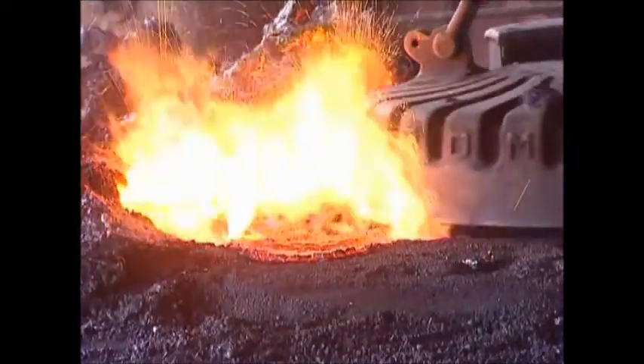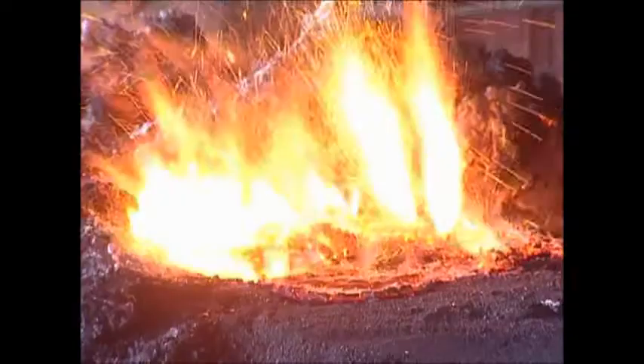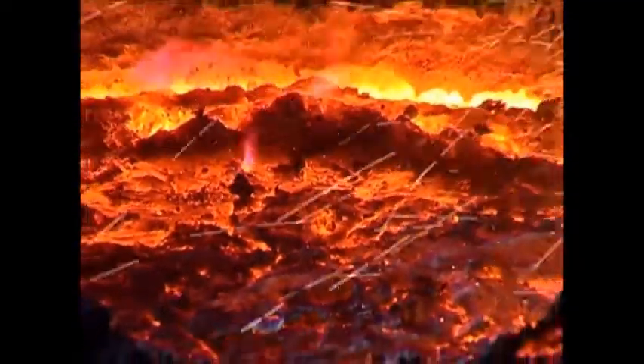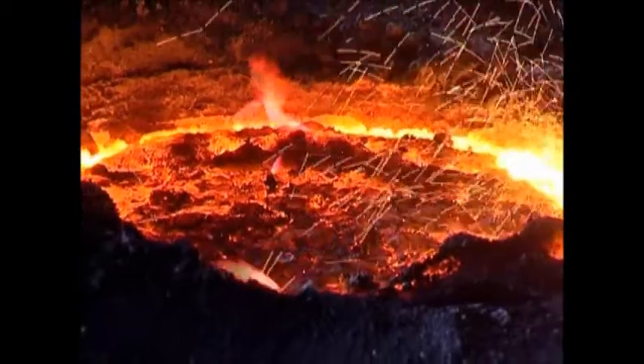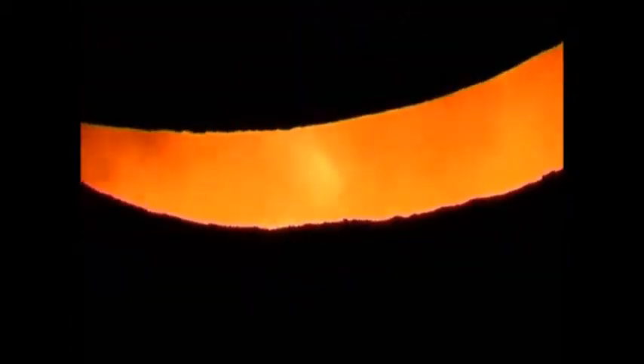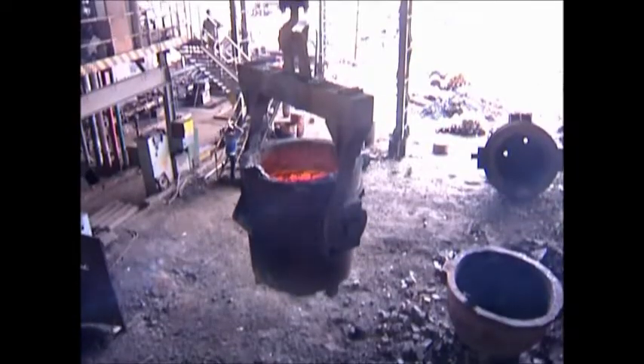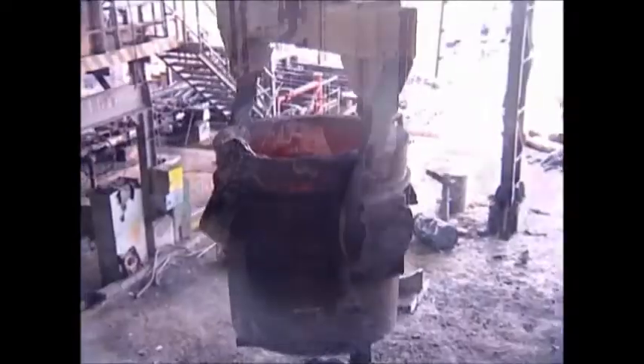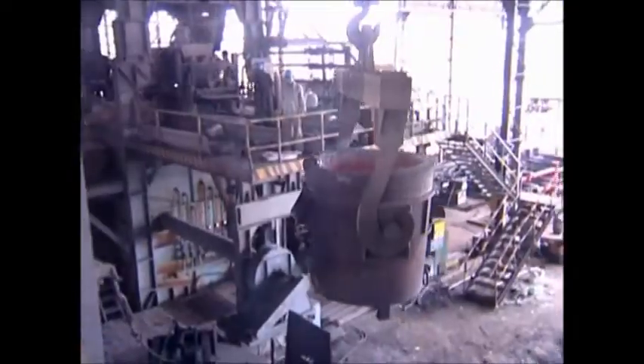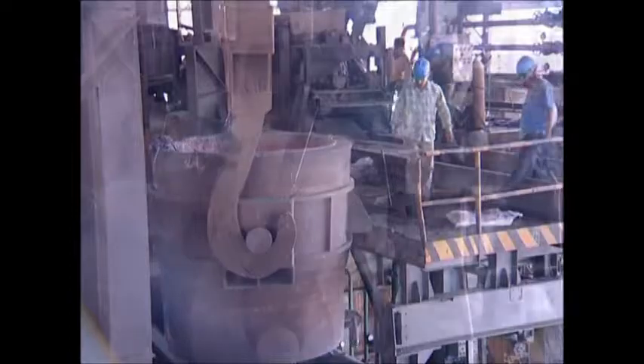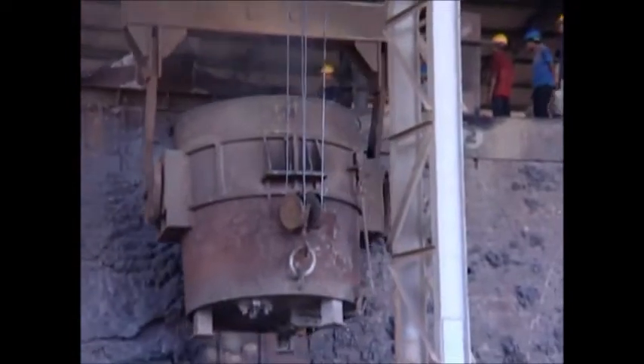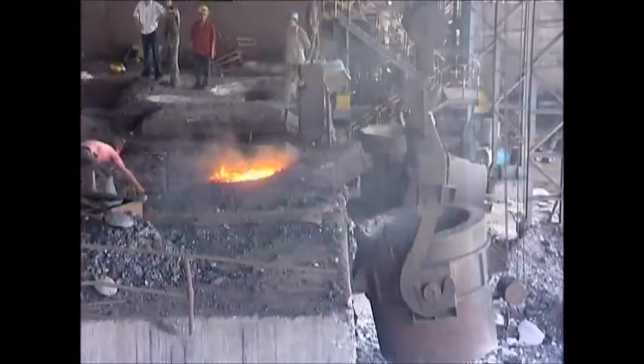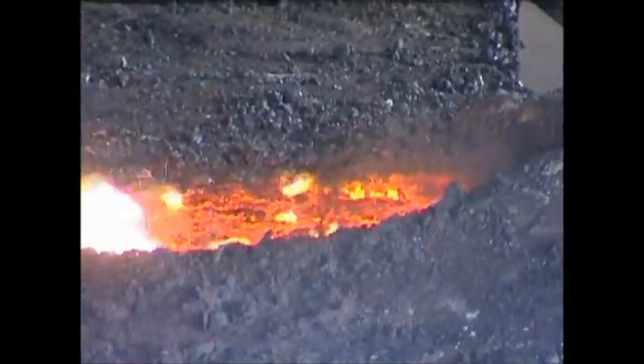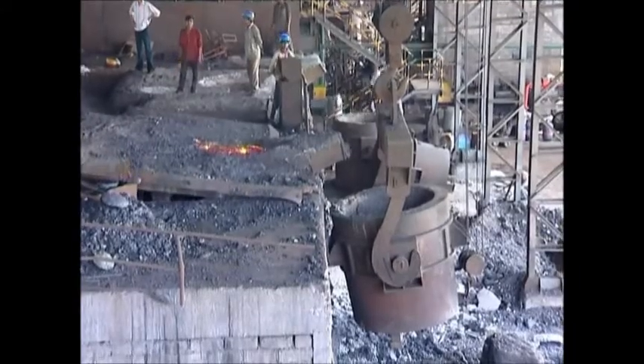The whole process of melting takes approximately 2 to 3 hours, and when the liquid metal is heated to 1670 degrees Celsius, silicomanganese is added into it. After that, the ladle is brought over it, and all the liquid metal is poured into this ladle. This ladle has to undergo purging by argon gas in the concast section. After purging, the temperature of the ladle is again taken. The temperature is maintained at 1650 degrees centigrade, and it is placed at the concast machine.